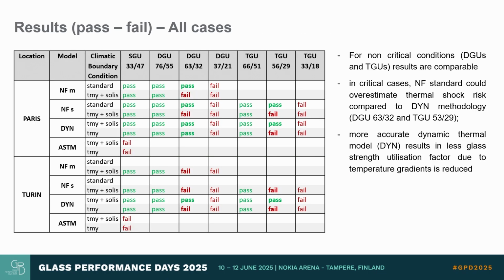This is just a summary of the results for Paris and Torino for the different models. So the French manual, the simplified, and our dynamic model. The DYN stands for dynamic model. And then the ASTM for single, double and triple glazing units for different boundary conditions. So the standard is the French national standard within French territory, and then the TMY of just clear sky and the real TMY for the two locations. What you see here is just a pass or fail for the IGU. It's simply saying whether we could have thermal shock in that IGU or not, but actually behind this we calculate all the delta T for each glass layer. So this is one result, but then we went deeper to understand what was happening.